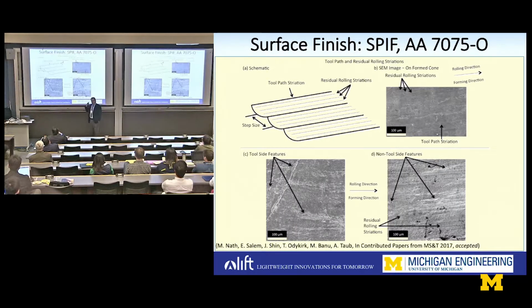But here is, and I said I'd make some interesting remarks about how a material scientist approaches a problem like this rather than a mechanical engineer. Maya was showing some fracture surfaces. We were looking at the structure. I said, wait a second, in the SEM, what's that on the side? It turns out nobody, and this field's been active for a decade, was looking at the surface finish of the parts. And what she discovered was, not surprisingly, and this is something we're looking at hard, you have